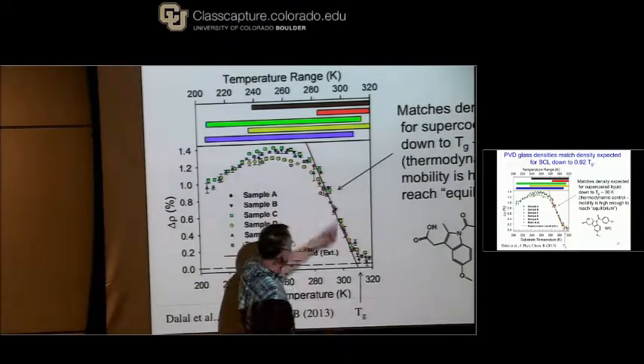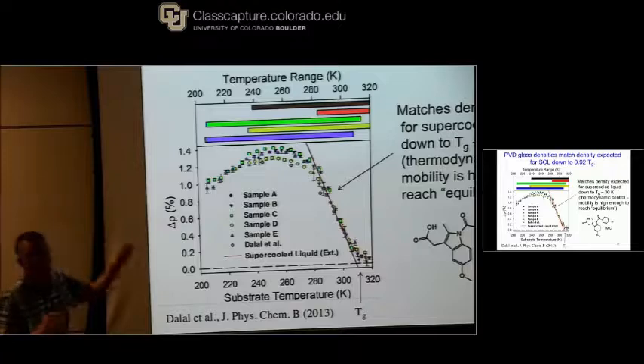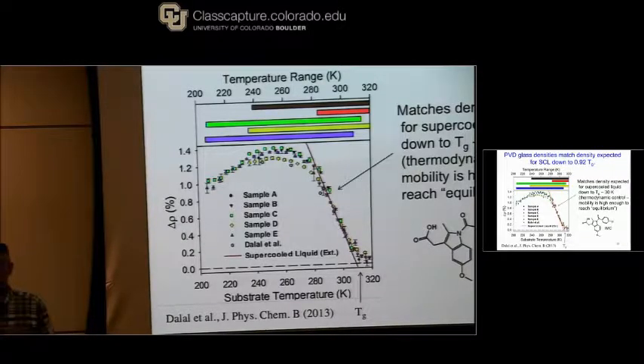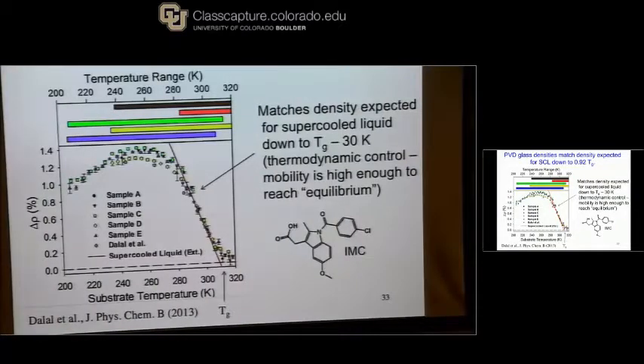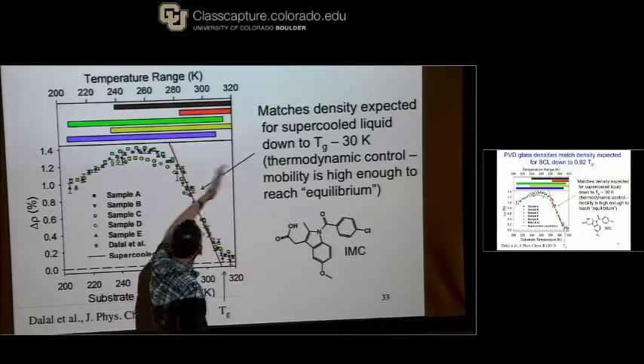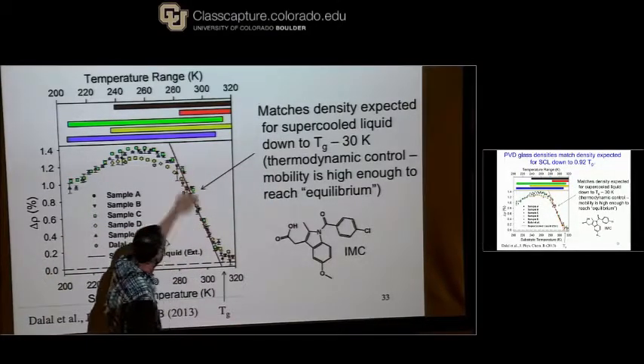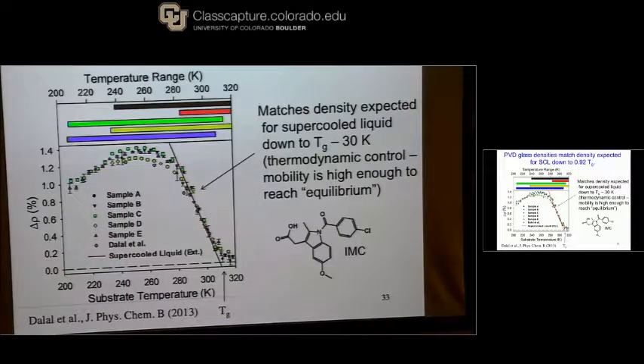This red line: for this molecule, I know what the density of the supercooled liquid is, and I can do a linear extrapolation to say what I expect the density to be for the supercooled liquid below the conventional TG, where it can never be measured. That's the red line. Down to TG minus 30, right about here, my vapor deposited glasses have the density that I expect if they were the equilibrium supercooled liquid.